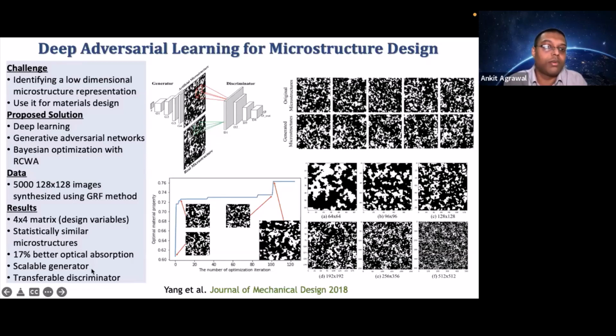And there were some other side properties which were beneficial, like scalability of the generator. So the same generator could be used to generate different resolution images, which previous works could not do because of fully connected layers. But we start with a noise vector here, which is just 4 by 4, 16 random values. But if we just increase this to, let's say, 5 by 5 or 3 by 3, or we change it accordingly, we can use the same network to have different resolution of images, and all of them are statistically similar. So just a quick example of what GANs can do in this domain. And of course, we have some follow-up work, which is right now under review, which speeds up this optimization loop.